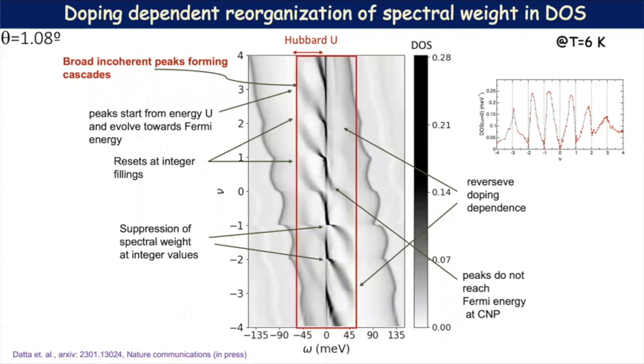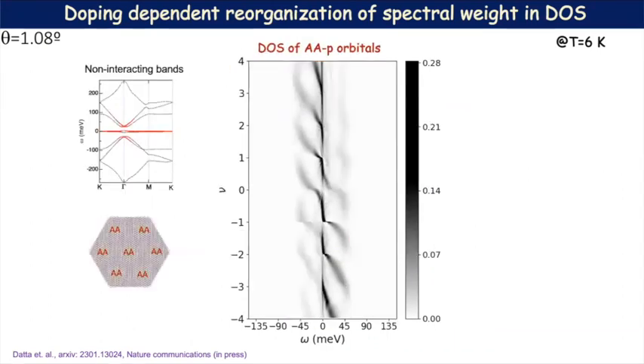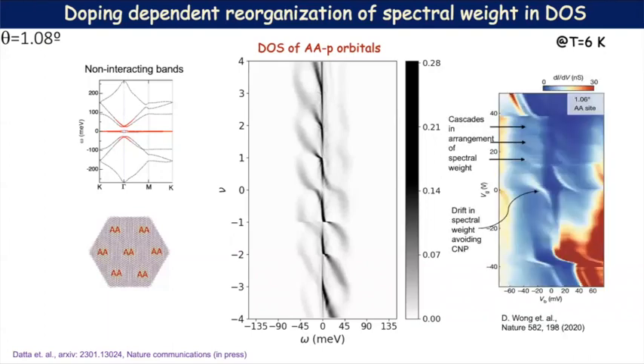Now, this part of the picture comes from the AA orbitals, which you can see from this orbital resolved density of state. These AA orbitals are in the AA stacking region, and they are in the flat bands in the non-interacting picture. If you now look at the experimental picture, which they have from the AA site, you can see there is quite good agreement. You can see these cascades in the arrangement of spectral weight, and you can see this drift in the spectral weight, which is nicely comparable with what we have from our calculation.